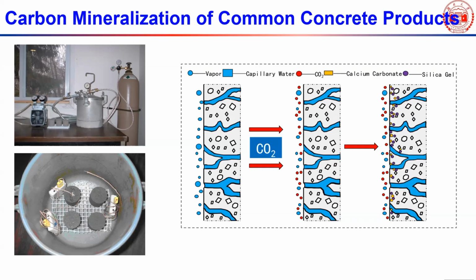This figure demonstrates my initial testing. We compacted some small cylinders using the block mixture, which is very dry, and then exposed them to CO2. You can see that only the surface carbonates. So after molding or compaction, how can we remove the moisture in those capillary pores? Because without moisture, it is a very porous mixture, so we can let CO2 go inside very quickly, right?